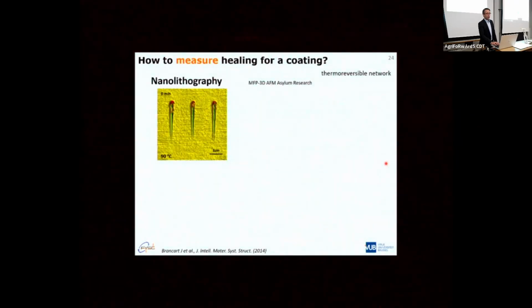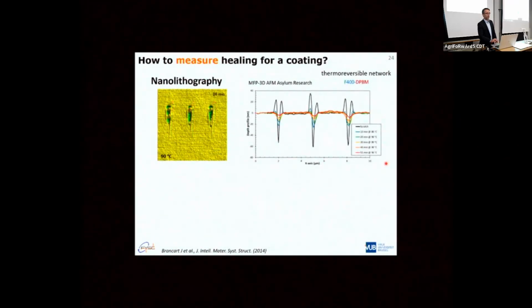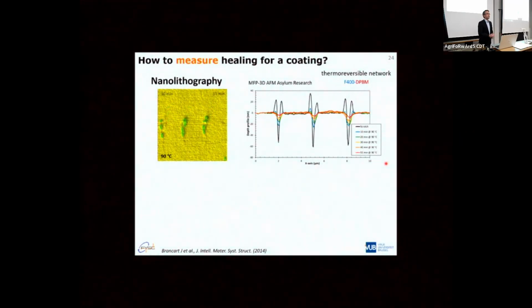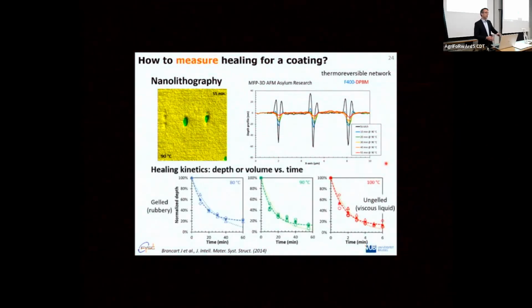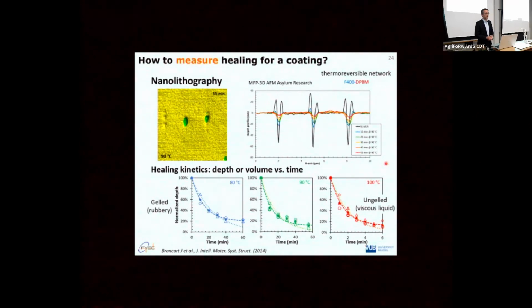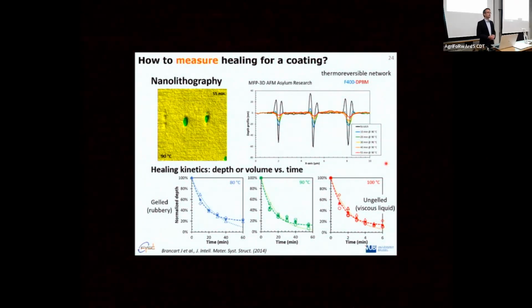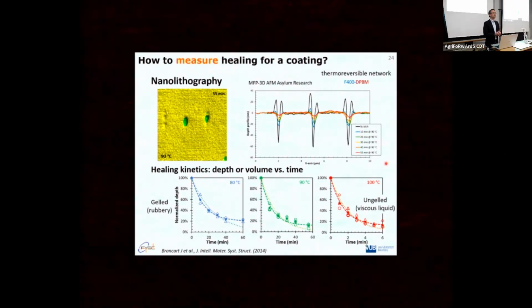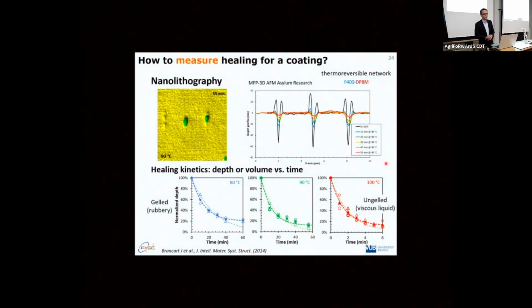How to quantify the healing, how to measure it. I mentioned that you could go to nanolithography for scratching the material and then to look at the healing of such scratches. You could really measure their size, measure their depth, their volume, and quantify it. That's what we did in these graphs. They date back quite some time, but nicely show that you can start applying kinetic evaluations, or time constant evaluations, on this kind of healing behavior. Maybe this is more a sealing behavior than a healing behavior, because we show that the crack disappears. We don't show that the properties of the material go back to the same properties.